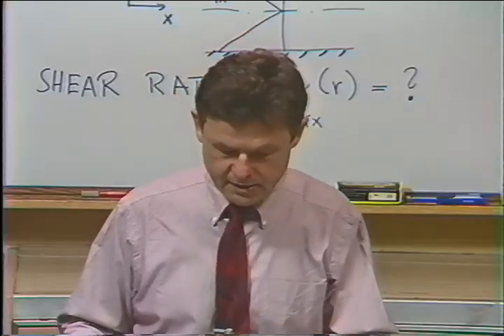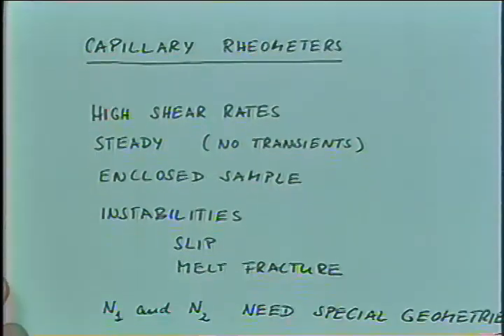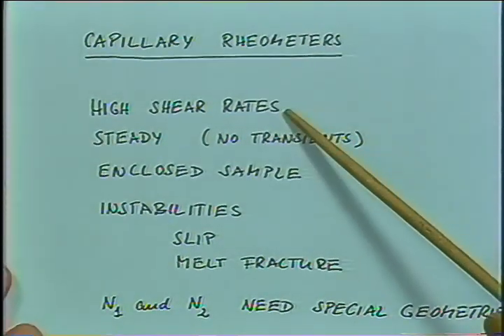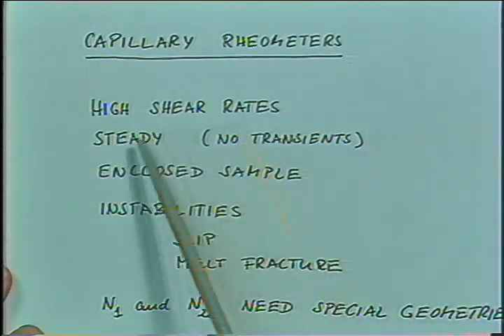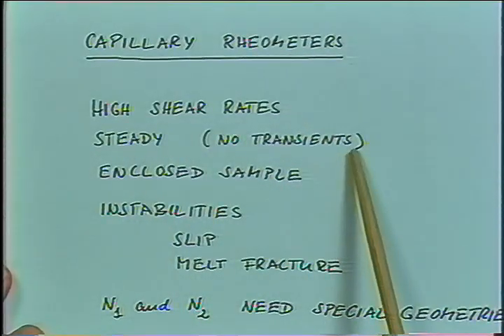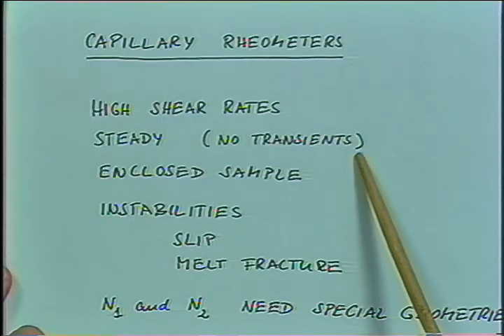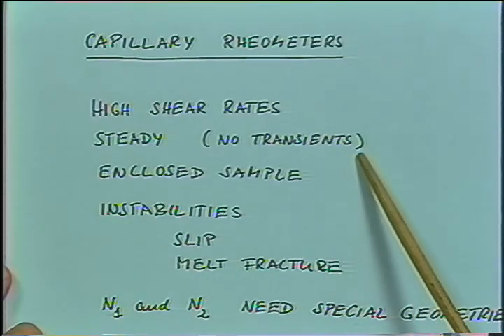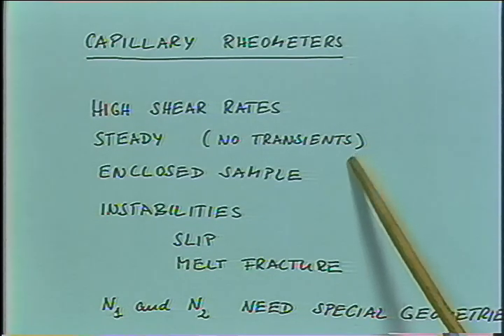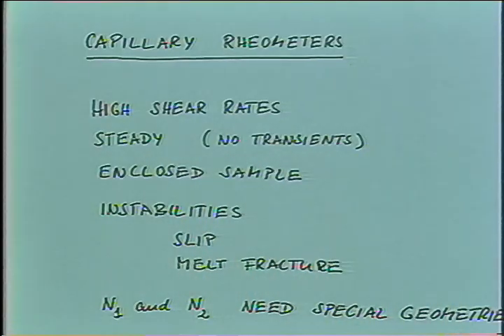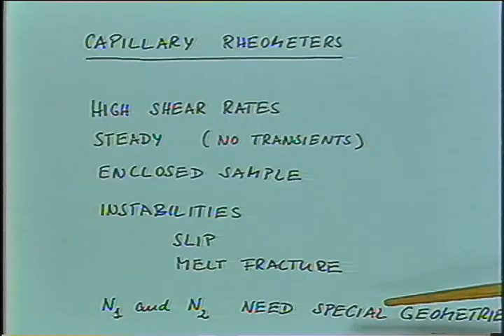So in summary, the capillary rheometers are very useful to measure at high shear rates. The experiments are limited to steady shear flow. We cannot do transients. Well, you could maybe pulse your pressure gradient and push liquid back and forth in the capillary and analyze that. But if you have a steady motion through the capillary, then you just get the steady state properties.